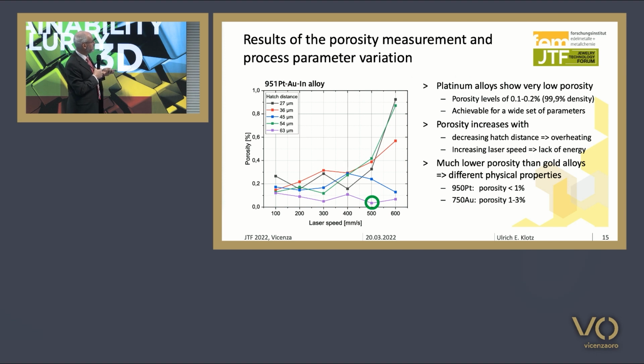While an increasing laser energy is also increasing the porosity, increasing laser speed is also increasing porosity, because if the speed is too high, the energy is missing.